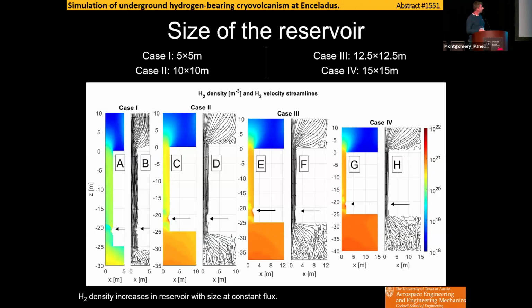And the last parameter we looked at is the size of the reservoir. So we considered 4 cases. The first one with a very small reservoir of 5 meters high, 5 meter radius, 10 by 10, 12.5 by 12.5, and 15 by 15, with the contraction always located at the same height. The depth is the same in all those computations. When you look at the H2 number density on the left, and also A, C, E, and G, and the velocity streams, we can see that the H2 plume at the surface is not affected by the size of the reservoir as long as its typical length is much bigger than the width of the conduit.